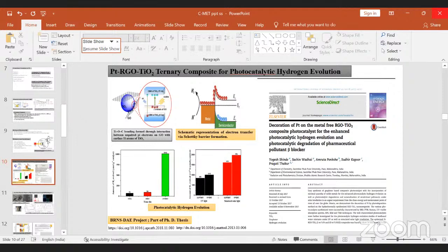Then we thought that as RGO is recently being used as a very efficient material, we have incorporated here reduced graphene oxide, which acts as a very good electron sink, and it has also been shown to have increased light absorption in the visible light. So we thought we can prepare a ternary composite of TiO2 with platinum and RGO, thereby reducing the percentage of platinum in the system but still getting higher efficiency. Here we have used 1% platinum and 10% RGO in this ternary composite, and we could find out that